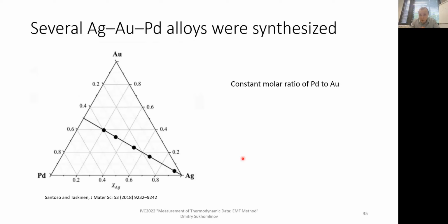This study was conducted by Dr. Santoso and Professor Taskinen a couple of years ago. So first, a series of alloys was synthesized. The molar ratio of palladium to gold was constant in all of them, 1:1. But silver had been varying from high silver, around 80-something percent, down to 20% silver.